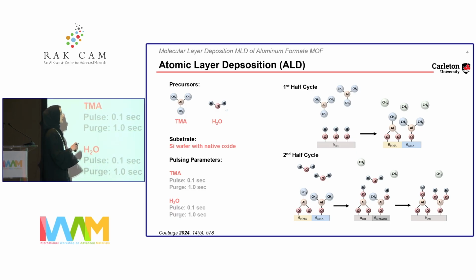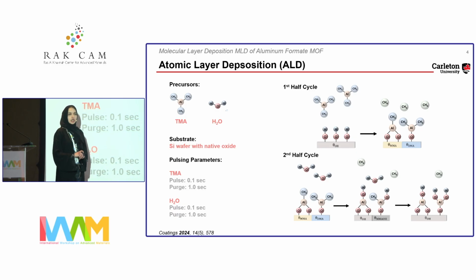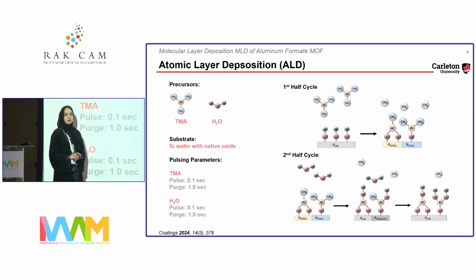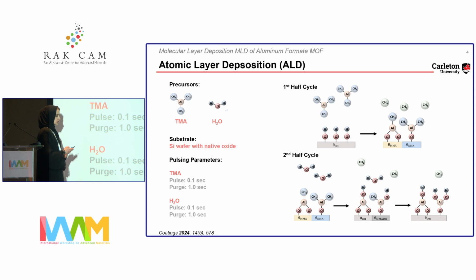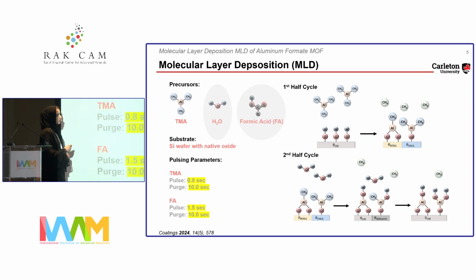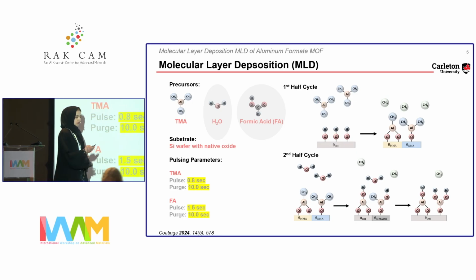If you bring in the second precursor, that's the water, it's going to react with the aluminum on the surface. It does not accumulate, one layer thick. Everything extra gets purged outside the system. So we wanted to adopt this methodology, but by exchanging water with just formic acid. So this is what we did here.